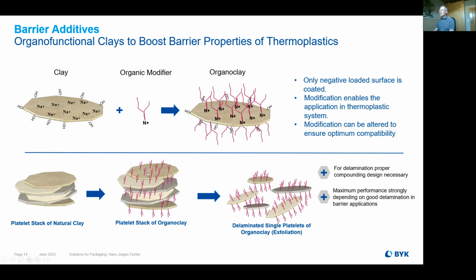I'll keep it simple and not focus on the chemistry. We exchange some ions and bring in these red dots or red lines which you see at that point, with some organic. With this organic, we push the platelet structure a little bit further apart. That means we make our life easier during the compounding step to exfoliate, as it's called. We can also call it dispersing your platelet structure in the matrix. That is really the trick. The organic should fit the polymer, which is also quite important, especially regarding polarity and thermostability.